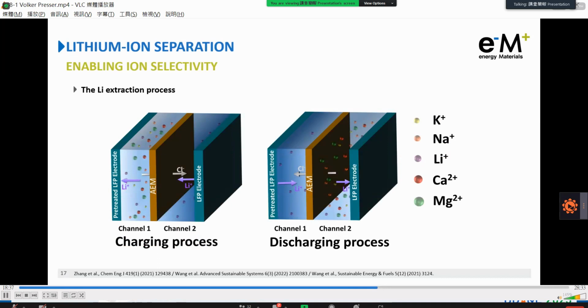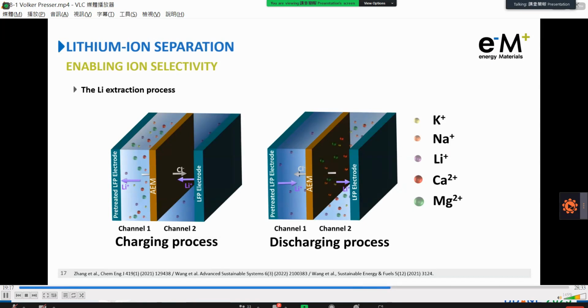An alternative system that also operates intermittently, in a swinging chair or rocking chair geometry, uses lithiated and delithiated LFP separated by one anion exchange membrane. There you uptake and release lithium in channel 1 and channel 2, and chloride ions can pass through the anion exchange membrane for compensation. This generates, during the charging process, an increase in ion concentration in channel 2, whereas in the discharging process, you uptake and release in a mirror image. So channel 1 becomes the one that gets enriched.